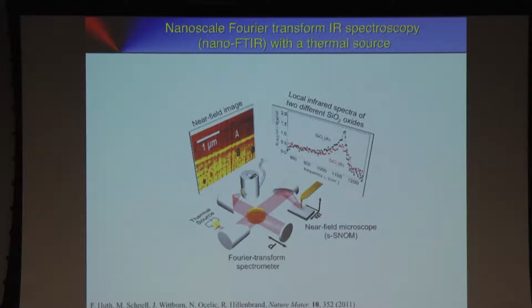And after a painful time for Florian, we got some images. So that's an image of two oxides. Here the interface of the oxide. If the tip is at a fixed position, at a white light position, then we get an image. We can clearly see that we get a nanoscale resolved image. Then we can place the tip on A and B, two different positions, and we really got some spectra, pretty noisy, but we see that the two oxides are different here. So this is a pretty tough experiment. It's not very practical, and I would not recommend to do it.